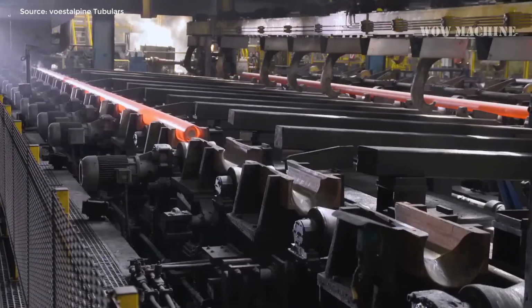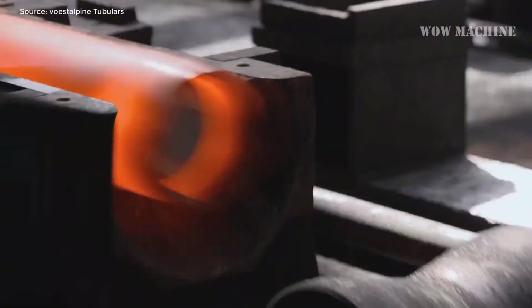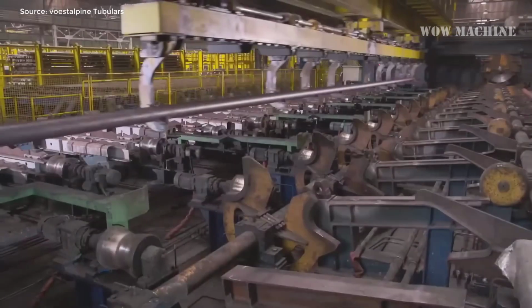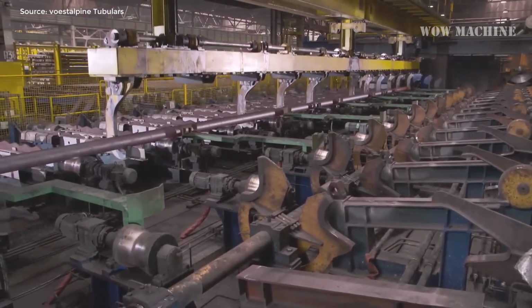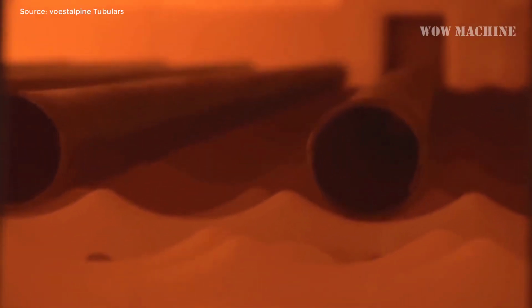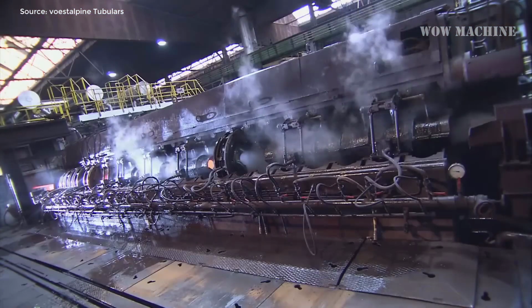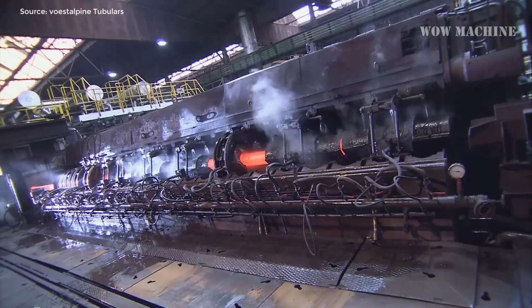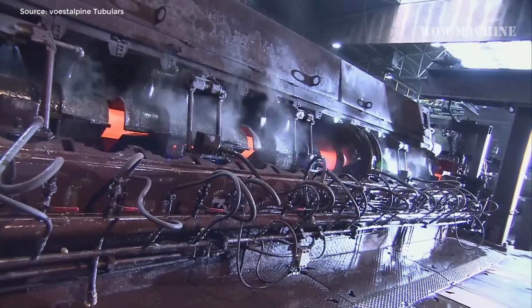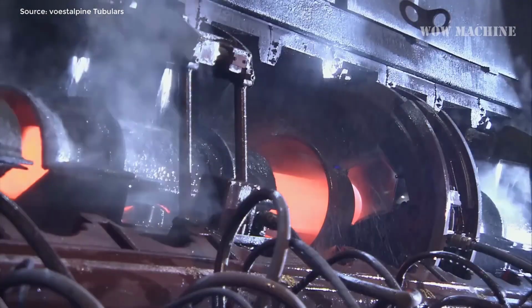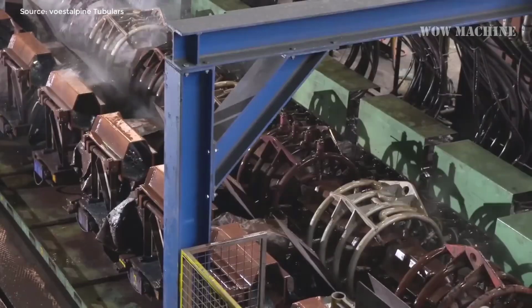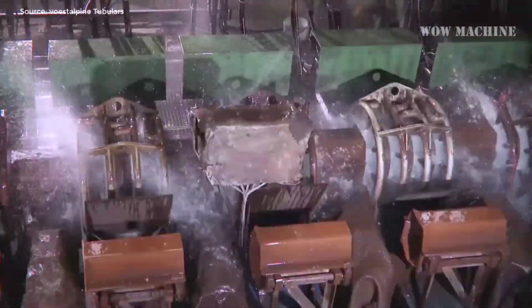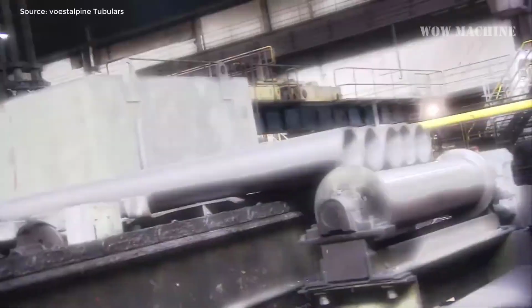Stretch reducing mill. The hollow, still containing the mandrel bar, is subsequently passed through a relay system where the rolls expand the hollow, allowing for the removal of the mandrel bar. Before entering the reheating furnace, the wall thickness of the hollow is monitored using a radiometric gauge, ensuring uniformity along its length. The hollows are then heated in a computer-controlled walking beam furnace, preparing them for the stretch reducing process. This step involves rotating the hollows as they pass through the furnace to ensure consistent heating.